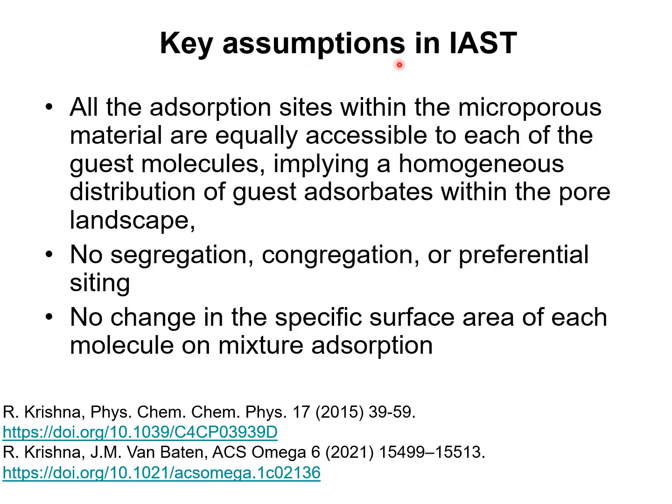We summarize the key assumptions that are made in development of the IAST. All the adsorption sites within the microporous crystalline material are equally accessible to each of the guest molecules, and this implies there's a homogeneous distribution of guest adsorbates within the pore landscape. There's no segregation, no congregation, or preferential siting of guest molecules within the pore topology. And the specific surface area that is occupied by each molecule remains unchanged in mixture adsorption.